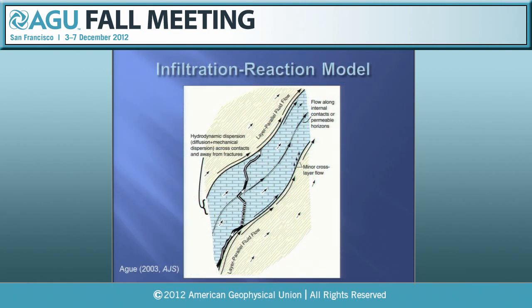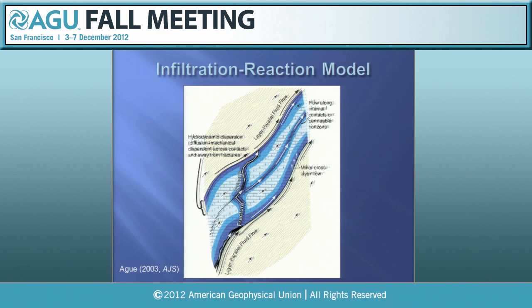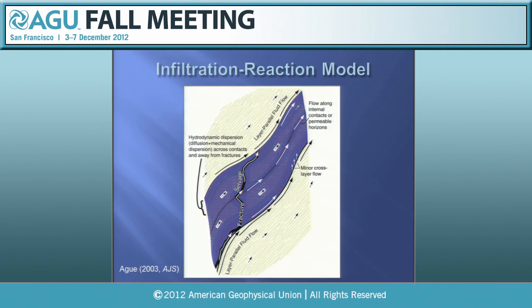So the kind of picture that evolves is where you have a lot of layer-parallel fluid flow. This is both in Connecticut and Vermont. There is some flow internally to the metacarbonate, some cross-layer flow. There's also a lot of diffusion and mechanical dispersion, flow along cracks too. It's very complicated. But as the water infiltrates into these layers, you get progressive mineral zones developing, most intense on the layer margins, until ultimately the whole rock is reacted and it continues to heat up until you hit the next suite of reactions. And John Ferry and co-workers have shown at this meeting, actually, that transport and infiltration between different carbonate layers can, in fact, drive very similar processes.